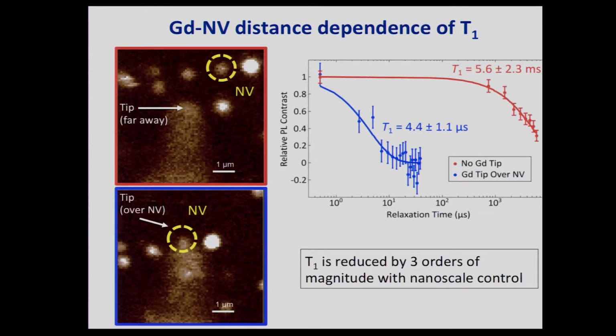So some of the data shown here: when our tip is far away, say a few microns away, we measure the T1 of the NV center, and we see that it's about 5 milliseconds. Then when we position the tip directly over the NV center in much closer proximity, and this NV center, by the way, is about 6 nanometers deep below the diamond, so the gadolinium and the NV are separated on the order of 6 to 10 nanometers, we see that the T1 is reduced to 4 microseconds, so we get a 3 orders of magnitude change in the relaxation time of the NV center.